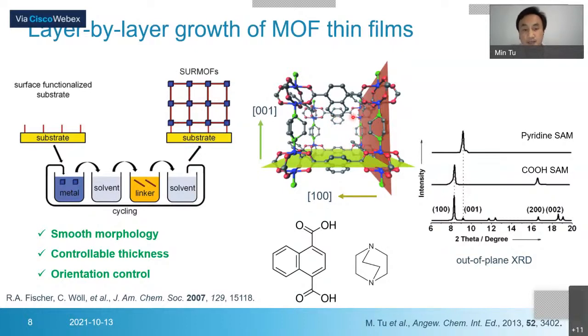And when using layer-by-layer deposition, with copper acetate and the NDC and DABCO solutions to deposit this kind of MOF on the surface, for example, on a pyridine-terminated SAM, we can see the growth in the 001 orientation. If we look at the structure, it goes along this direction because the pyridine can bind the copper acetate in this way, so it can grow along this direction. But if we functionalize the surface with carboxylate, then it can grow in this orientation. From the out-of-plane XRD, we can only see this reflection, which demonstrates a perfectly oriented film.